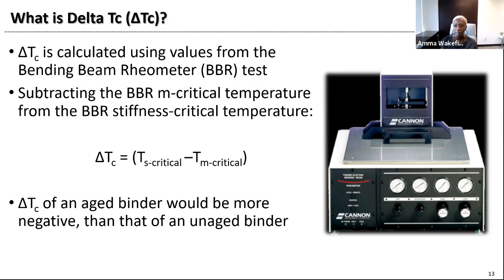So I mentioned that it's calculated from the test that's already done in the PG grading, and that's from the BBR test. That's the low temperature test. The critical temperatures that are determined from the BBR test for stiffness and m-value, when you subtract them, that's where you get the delta TC. And this is done through AASHTO R29. That's for doing the true grade for an asphalt binder.